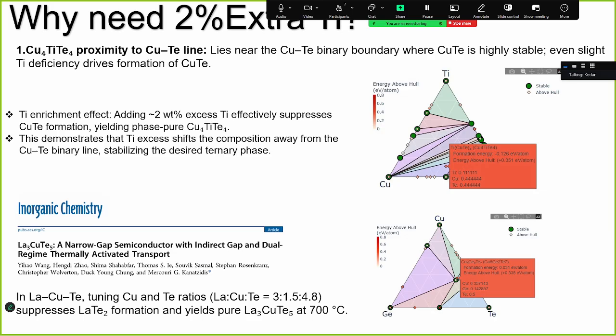What they do is they look at the stability of competing phases in the presence of high or low chemical potential of each element. I can translate that as saying, in the presence of extra titanium, because the chemical potential of titanium is high, the copper telluride is not likely to be formed. They usually look at vacancies, but maybe they have some ideas on the possibility of copper telluride stabilizing in the presence of excess titanium. And when you use those arguments, even with free energy or just simple formation energy, that should guide you to say, yeah, actually it makes sense.